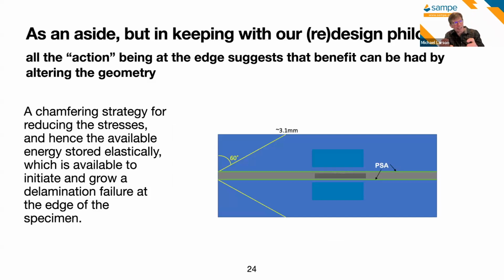So we can engulf that zone into a process zone that I believe we can characterize a boundary with our J integral domain that will capture what's going on. And then as the delamination proceeds, we'll see in a minute, it proceeds in a very self-similar sort of manner, continuing that justification. This is where I mentioned at the beginning that although the focus is choosing the right adhesive, seeing that massive shear at the edge told us that maybe we could look at a change in geometry that might help limit the onset of failure.